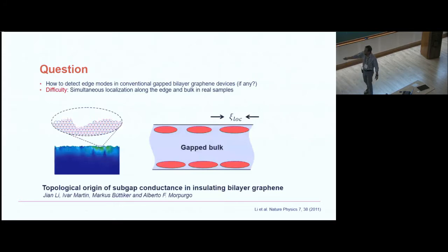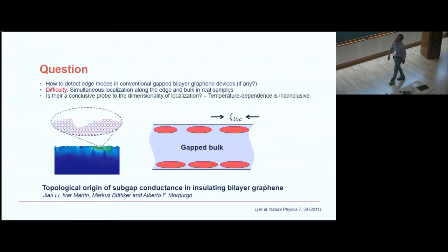So both localize, and that's what was essentially shown in a theoretical paper way back in 2011, showing that the gap is in the bulk, but the edge is also insulating. So it becomes very difficult experimentally to say whether the electrical transport is occurring through the bulk or through the edges. So we asked the question, is there a probe which can tell me exactly where the conduction is taking place?